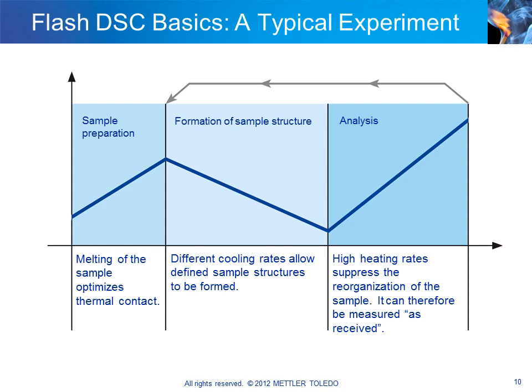Both the cooling and the heating segments are measured and can be repeated more than 100 times in a measurement program using different scanning rates. This allows the cooling rate dependence of a crystallization process to be measured in a very short time in a single measurement program.